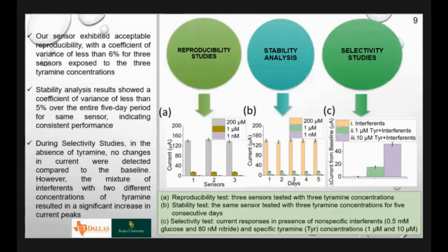We also tested reproducibility and stability. The first graph down here shows 3 different sensors for different concentrations, and you can see a slight variation, just about 6% variation in response. We also tested the stability of the same sensor for 5 days, at 200 micromole, 1 micromole and 1 nanomole, and we tested this for 5 consecutive days, and the variation is just about 5% within the sensing range.